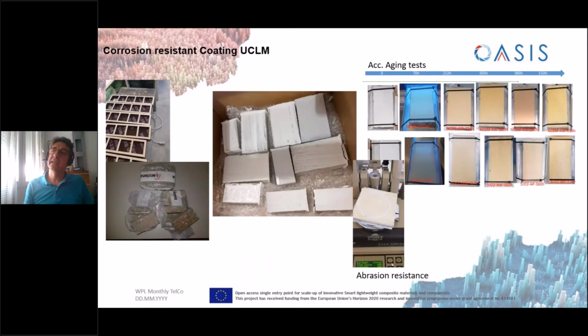In parallel, Castilla-La Mancha is developing a nano-enabled corrosion-resistant coating to further protect concrete reinforced beams in very aggressive environments. They are optimizing the coating formulation and the coating process. They are using different types of nanoparticles, going from nanosilica to titanium dioxide, and also different types of amorphous carbon particles. These coatings are validated at lab scale by means of several tests: Taber abrasion, accelerated aging test, adhesion, water absorption test.